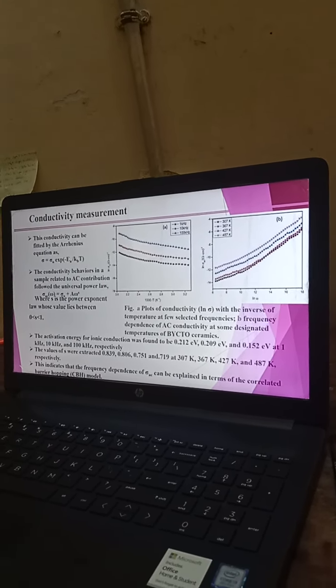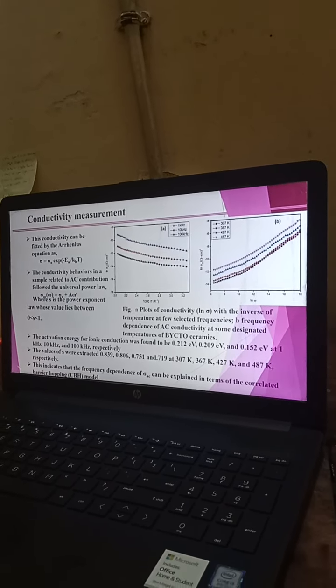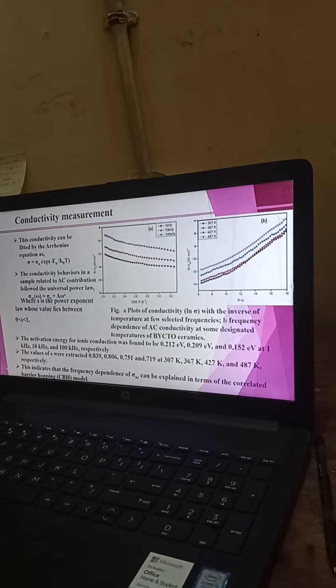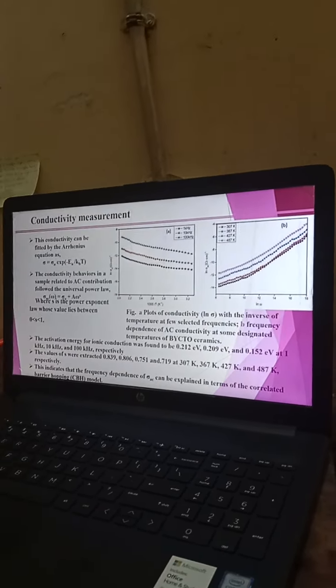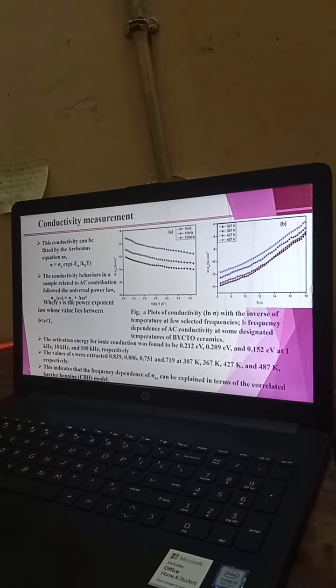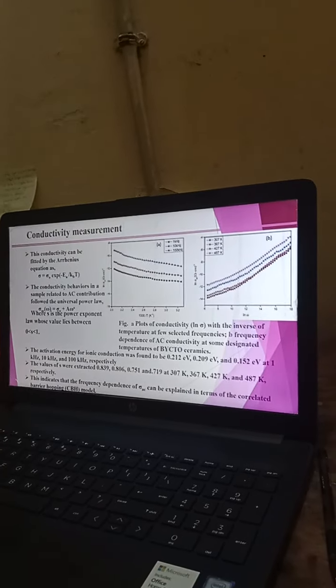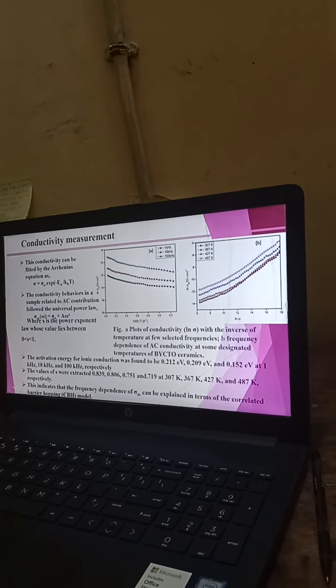Conductivity measurement. Figure A and Figure B represent the conductivity of the BYCTO ceramic with respect to temperature and with respect to frequency. Figure A represents the conductivity of BYCTO ceramic with temperature. In this figure, we have seen the conductivity increases with increasing temperature. The conductivity can be fitted by the Arrhenius equation: sigma equals sigma naught exponential of minus EA upon KBT. The activation energy for ionic conduction was found to be 0.212 electron volt, 0.209 electron volt, and 0.152 electron volt at 1 kilohertz, 10 kilohertz, and 100 kilohertz respectively.